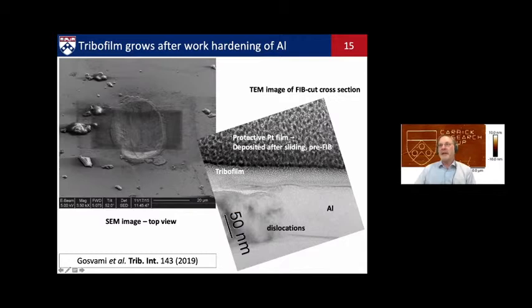And when we look at that in a cross-section in transmission electron microscopy, we see the aluminum, we see the tribofilm, and we see a lot of dislocations. So what that tells us is we first indented the aluminum. It then work hardened. Aluminum is a classic work hardening material. Its strength goes up as you move and compact and densify dislocations from deformation. So we think that what we were able to do was locally increase the hardness by the sliding action. And that's what led to the stiffening and strengthening of the substrate that then allowed the tribofilm to form.